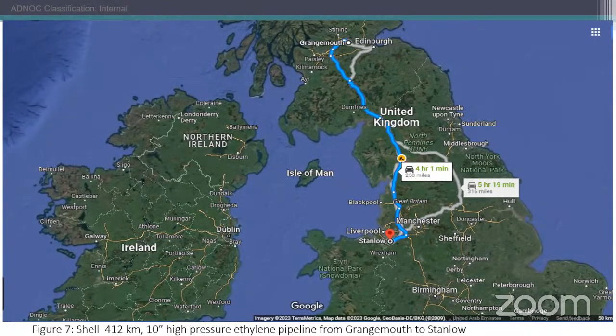And from the test station, they used a coupon to monitor if this high voltage transmission line was interacting with the pipeline. They discovered that the alternating current density in this section was way more than the allowable limit. And to this extent, it could corrode the pipeline. So it could cause this form of corrosion.